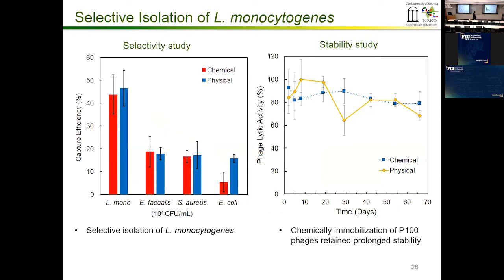So here is a demonstration of selective isolation of Listeria. The challenge with the magnetic particles is they can physically attach to any bacterial surface or any sort of bilipid membrane. So you end up getting all the non-target bacteria to some extent anyways. But our results showed that you have a preference to Listeria if you have the Listeria specific virus. So it does capture most of our target analyte, and then a little bit of some of the other organisms as well. And this requires further optimization, to block out the sites so non-specific adsorption doesn't happen.